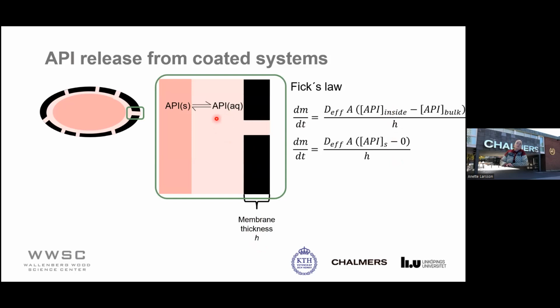Before I continue now, I also should remind you, when you have this equilibrium between a solid API and a saturated solution here, this means that you have locked the concentration in here. That means that it corresponds to the solubility. So this will not change as long as you have active pharmaceutical ingredient in a solid state left. Since the bulk concentration is very close to zero, we can put a 0 here, and we have then the diffusion coefficient here, and I will come back to that later, and also the area of the unit. And all these factors control the mass transport over this membrane.